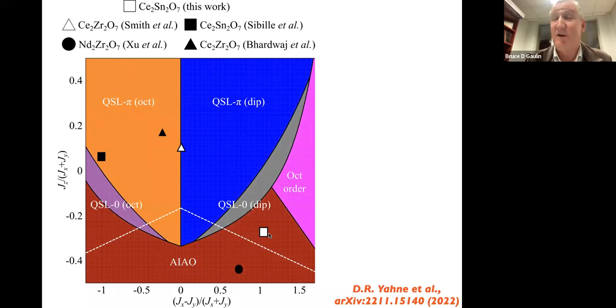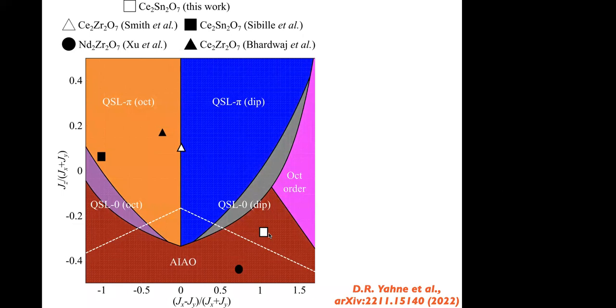Do you have any idea about the anisotropy of the G factor for this effective spin? Yes. It's very anisotropic. In fact, there only is a Z component, and the G factor GZ is about 2.5, I think. I'm going by memory. 2.57, yeah.